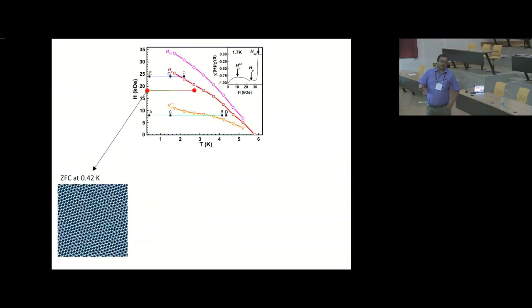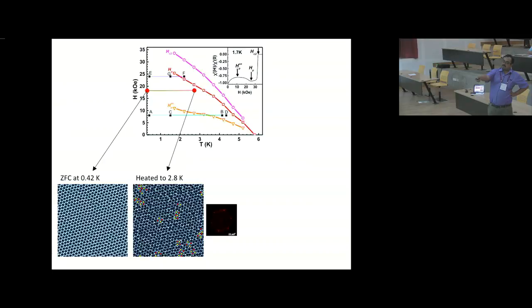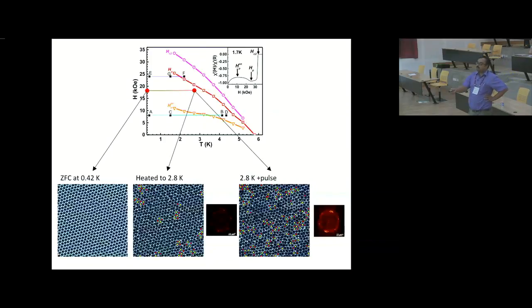Now, okay, there is a catch here because I am dealing with a glassy system, and I have hysteresis everywhere, so it becomes difficult to separate out hysteresis which is from the lack of glassy relaxation from the hysteresis from superheating and supercooling. So what I do to understand that is I prepare the vortex lattice here, and then I heat it without crossing any phase boundary. So here I am not crossing any phase boundary. I have some dislocations, and then if I apply a pulse here, I have more dislocations.